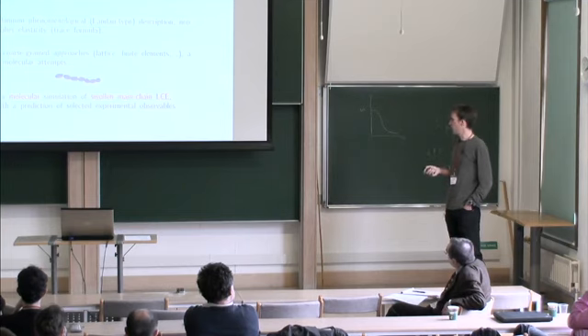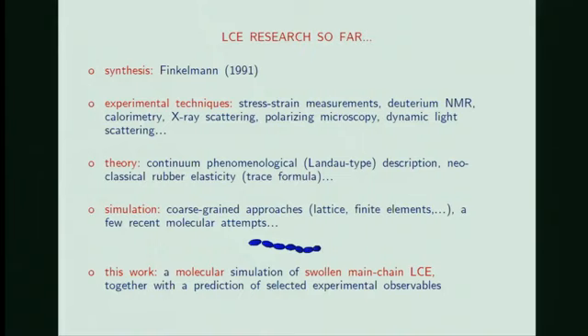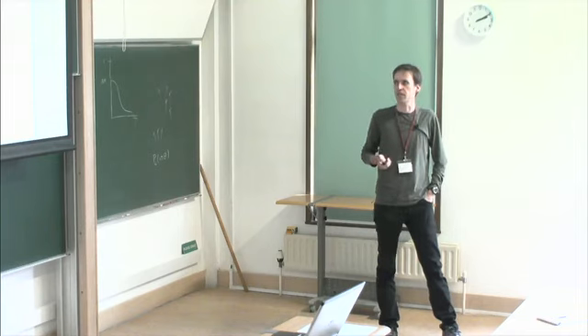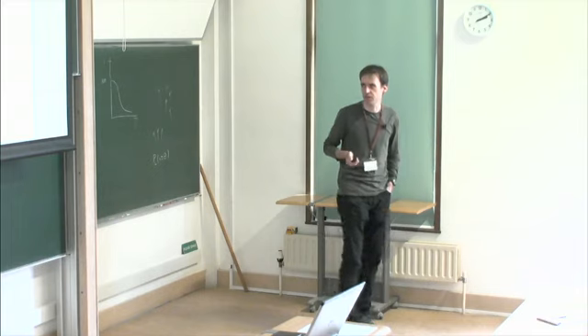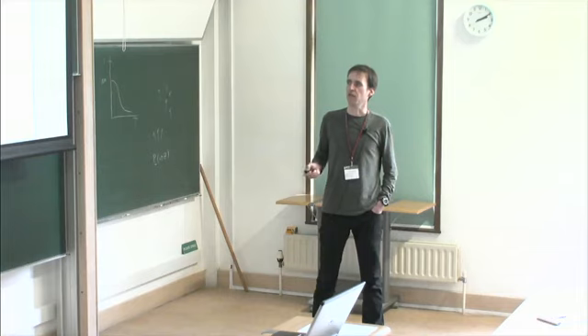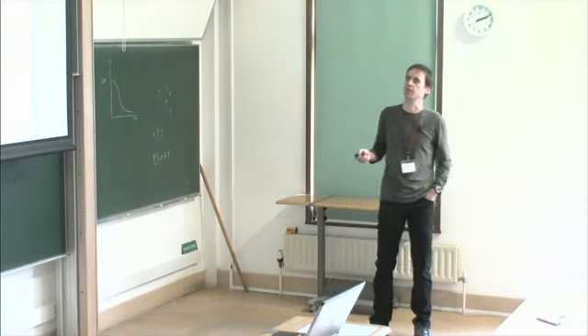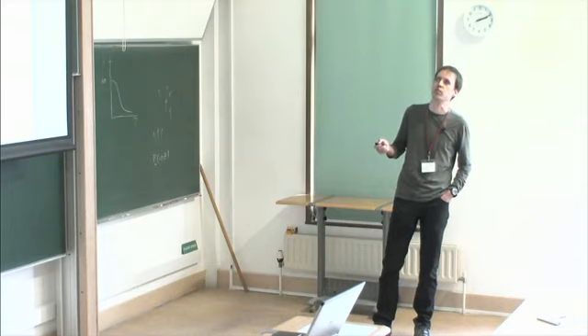We also deal with swollen systems. There is, for example, a series of experiments by Kenji Urayama where swollen systems were considered. But here there was also another, purely technical reason. Since polymer chains are typically not so easy to equilibrate, we thought that adding some swelling monomers, still of ellipsoidal shape, would increase the internal mobility of the sample while still conveying nematicity to the neighboring chains. So this also helps in our simulation. And of course, one of our goals was to try to predict selected experimental observables, some of which you can see here on this list.